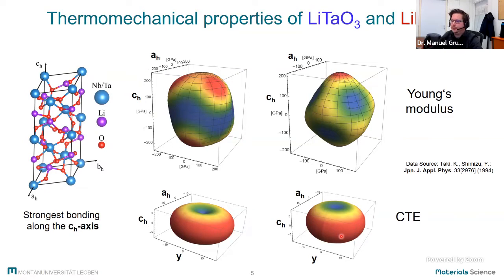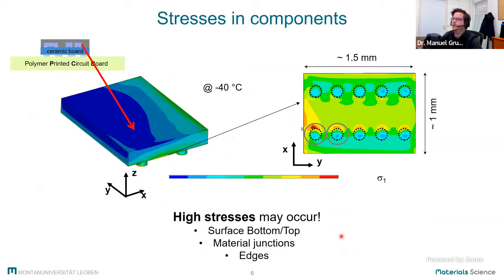So we have the highest Young's modulus in this direction together with the smallest coefficient of thermal expansion in this direction. If we now put these properties into finite elements simulations together with all the other properties, we were able to see that on our surface acoustic wave filters, the highest stresses are on the surface of these devices in the vicinity of solder balls, but also significant stresses at the edges, not so high, but at the beginning, we wanted to focus on those stresses on the surface of our devices.